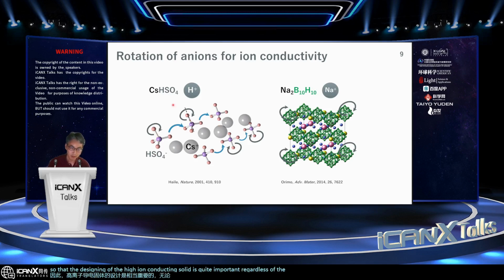The left-hand side shows a conventional, very high proton conducting solid, cesium hydrogen sulfate. This is a crystal structure made of cesium cations surrounding the HSO4 here. The reason the proton migrates very fast is that at a certain temperature, this SO4 minus starts to rotate very fast, and then the active proton migrates through this crystal. So this works as a very high proton conductor.